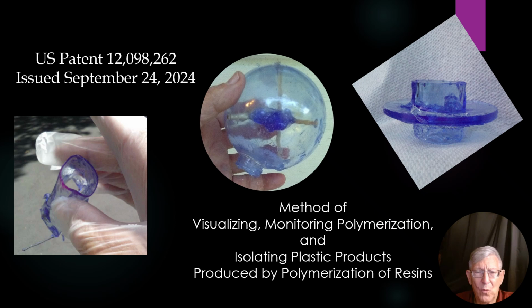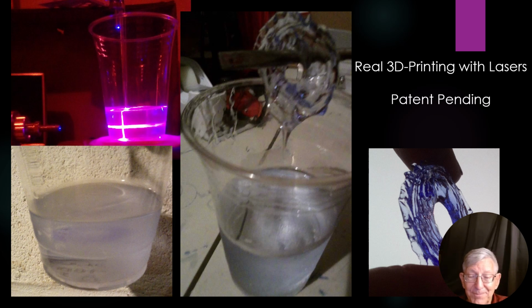In any event, what you see here are three examples of things that we have produced, either by proton beams or with laser beams, in which we were able to identify the fact that we actually have had reaction, and that reaction is demonstrated by the intensity of the color. So if you get a very small amount of reaction, you get a very small amount of color. If you have a very serious, extensive reaction, then you have a lot more color. So let's go to the next slide, and we'll see a better example of this.